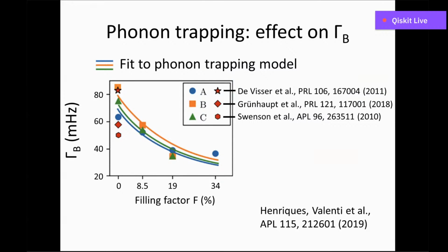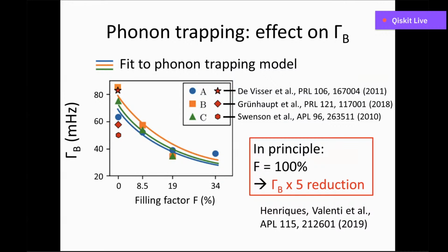The solid lines represent fits to a phonon trapping model that we developed in this publication, which allows us to extrapolate how well it would get for a full coverage of phonon traps or something that gets close to it. And in principle, this would lead up to a 5-fold reduction in the quasi-particle bursts. I think it's also interesting to note that the case for no phonon traps gives a burst rate that is comparable to the one observed by other groups with similar substrate size, as I report with the 3 red markers.